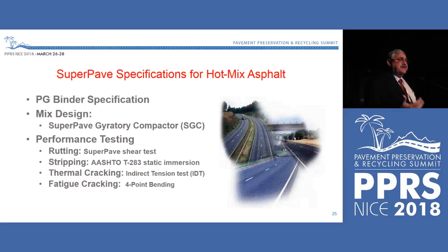We've added an additional performance criteria. We found out that the surface aging is a different failure mechanism, and we're looking at new specifications in the direction of changing rheology to understand brittle failures. You can see some of the papers by myself or Jeff Rowe that talk about that. So some changes are coming, and the test methods are also changing over time.